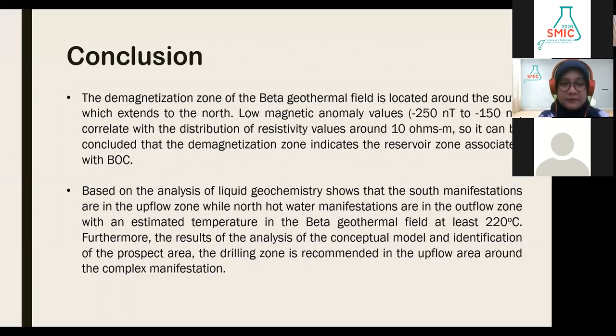Based on the analysis of liquid geochemistry, the south manifestations are in the upflow zone, while hot water manifestations are in the outflow zone, with an estimated temperature in the beta geothermal field of at least 220 Celsius. Furthermore, the result of the conceptual model analysis indicates the prospect area, and the drilling zone is recommended in the upflow area around the complex manifestation.